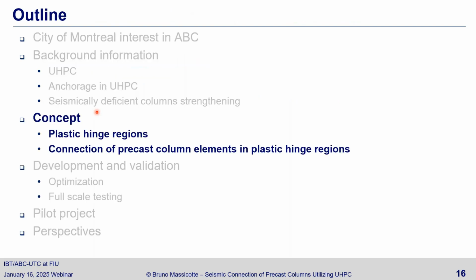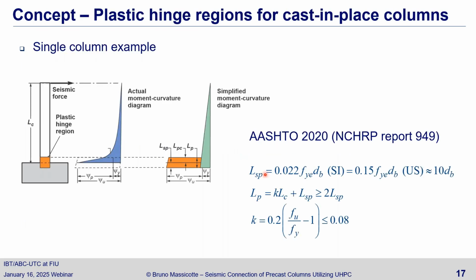So the concept is as follows. If you take a cast-in-place column, a simple column, and you look at the behavior in the plastic hinge region, if you have a not too long column, a short column, the plastic hinge will be spread out half and half, one half in the footing and one half in the column. This is given by this equation here in SI units or in American units. Roughly, the plastic strain penetration within the footing is roughly 10 bar diameter for conventional reinforcement. And that equation here is the one given by the AASHTO or NCHRP document to compute the length of the plastic hinge for computing the column behavior.